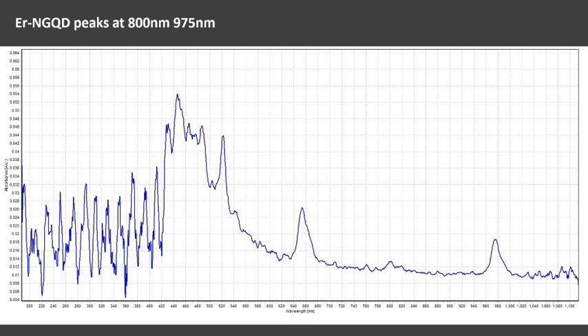This here is a graph of the absorption spectra for Er-NGQDs. You'll see that you have the absorbance in an arbitrary unit on the y-axis and the wavelength in nanometers. Remembering that the near-infrared is between 800 and 1100 nanometers, this is the area that we're looking in. We see two peaks that were important to me: a peak around 800 and a peak at 975. The reason those two stuck out is because the two lasers that we have to use in our lab are an 808 nanometer laser and a 980 nanometer laser. While they're not exactly at either of those lengths, there might be enough of a peak there that we could see some absorption at those lasers that we have.